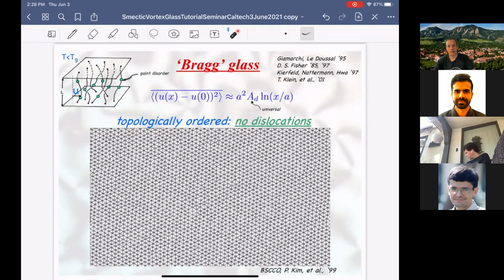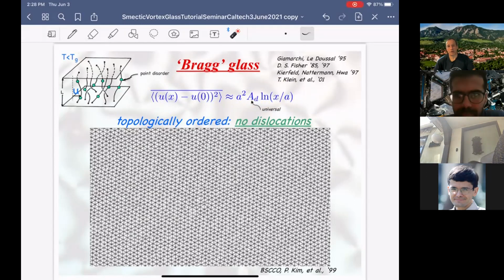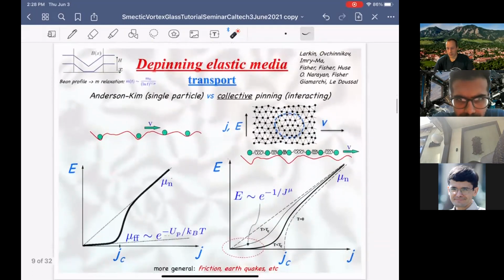you can do a very detailed analysis, and the correlations of the displacement display a log divergence below 4 dimensions, with a prefactor that's universal. So unlike the Kosterlitz-Thouless phase driven by thermal fluctuations, which only happens in 2 dimensions, this is analogous, except this behavior persists between 2 and 4 dimensions. So in particular it applies to 3 dimensions, and the prefactor is actually a universal number, unlike the Kosterlitz-Thouless transition. It's just a pure number. There are many other consequences of this, and let me touch on some of them.